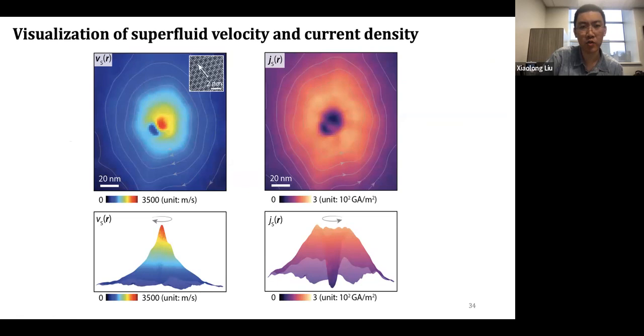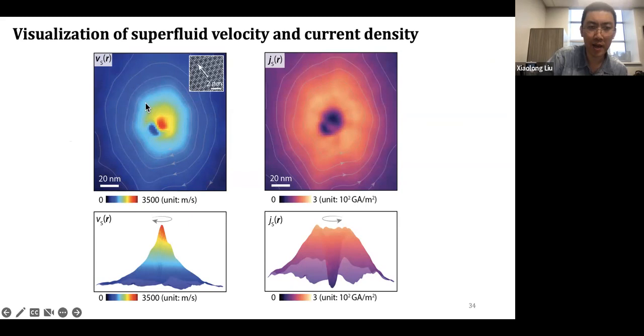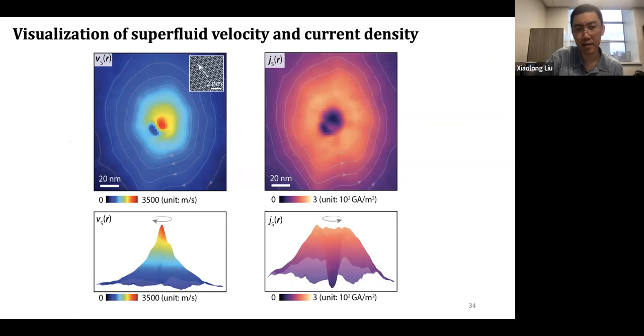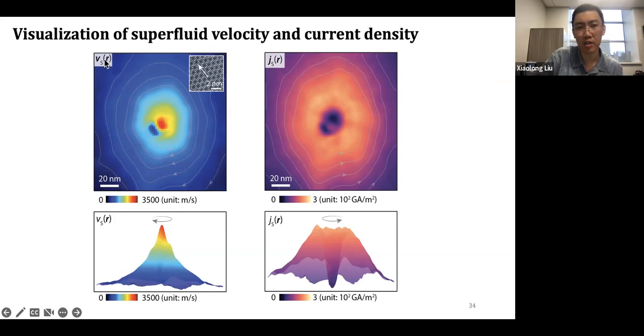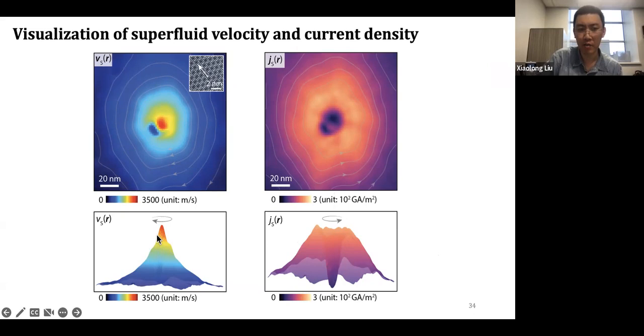With δE_k extracted, we can extract the velocity field of the flowing superfluid around the vortex. It gives a hexagonal pattern, and the fluid velocity goes up to even 3000 m/s — which is really fast. This hexagonal shape has been proposed theoretically since the 1990s and I believe this is the first time it is observed. We can then look at the superfluid current density by multiplying m·v_s by the superfluid density n and 2e, and it decays to zero at the vortex core — because the superfluid density at the core is zero, multiplying by v_s gives zero.